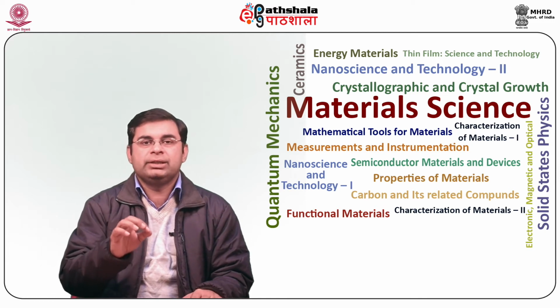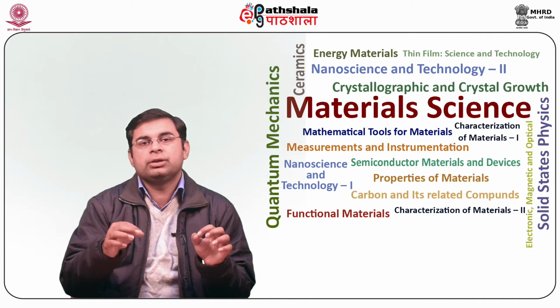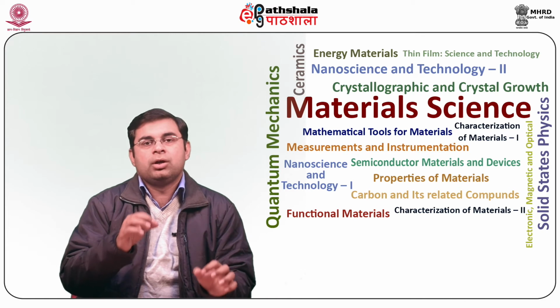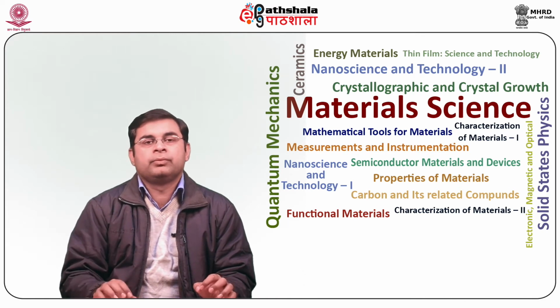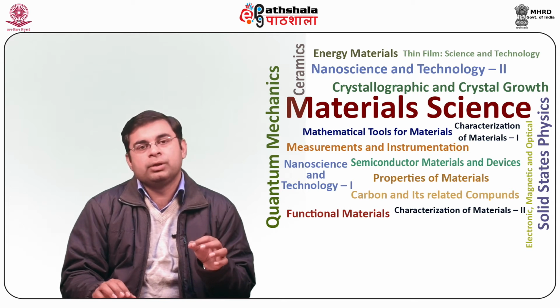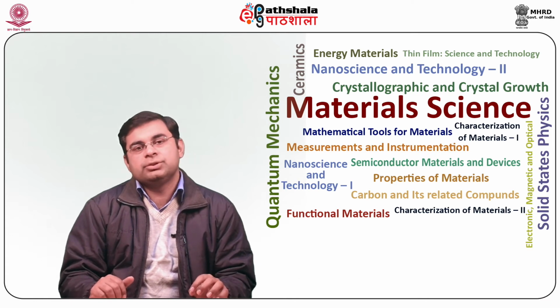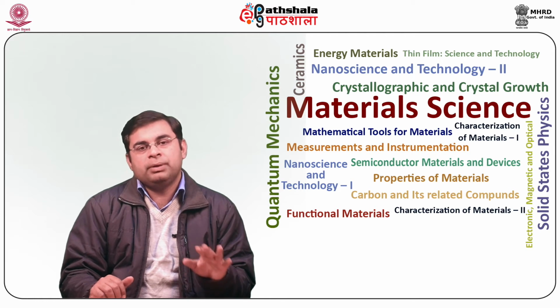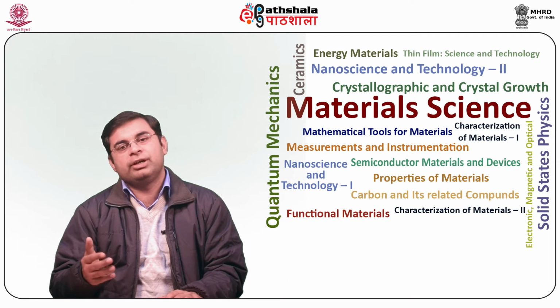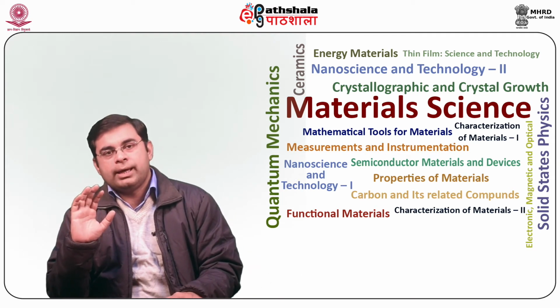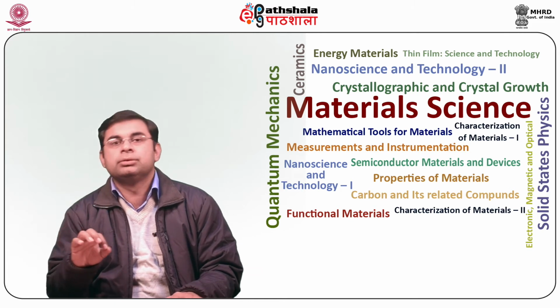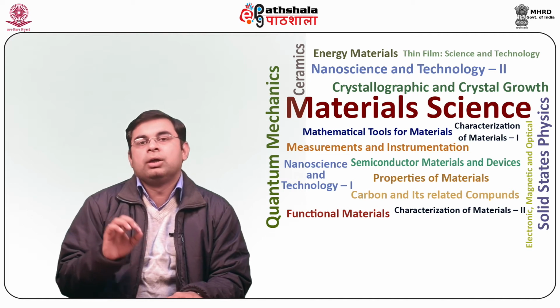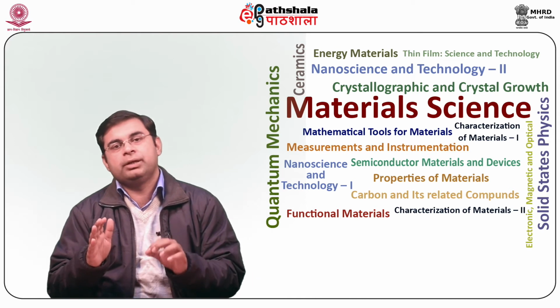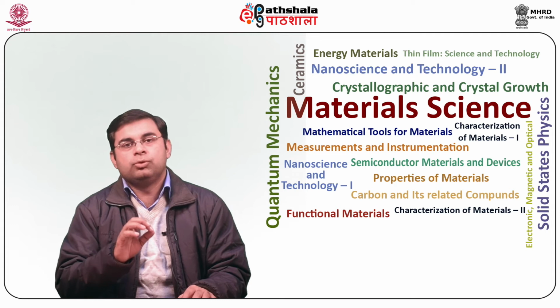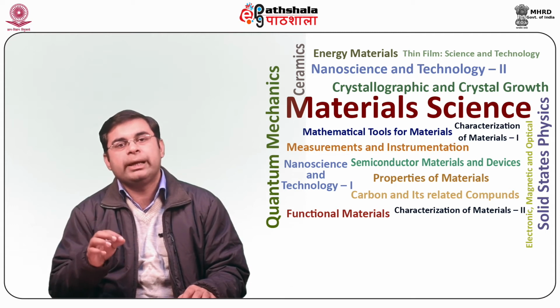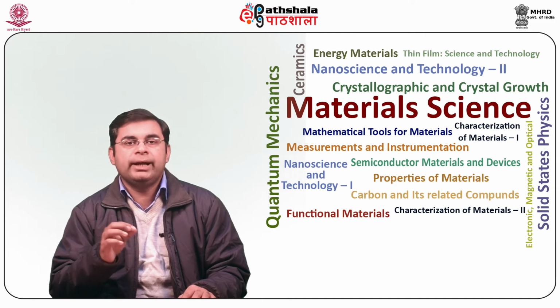Consequently, the alignment of bands in the semiconductor corresponds to a location relative to these surface states, which are already pinned to the Fermi level because of their high densities, and becomes insensitive to the metal. Many commercial semiconductors suffer from Fermi pinning phenomena, causing difficulties in device fabrication. Examples of these semiconductors include silicon, germanium, gallium arsenide, etc. Since the valence band in p-type germanium is pinned to the Fermi level of the metal, most of the metals form ohmic contact with p-type germanium and Schottky barrier with n-type germanium.